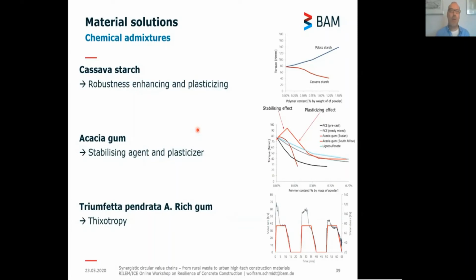And the other aspect that I was talking about were the chemical admixtures. All those agricultural wastes, before they can be converted into a reactive ash, often contain a lot of organic components, which can be converted into a chemical admixture. For example, we found out that cassava starch, other than potato starch, has a liquefying effect while it's still increasing the robustness. So here you can see the torque in a rheometer increasing with the dosage of potato starch, but you can see that the torque is decreasing with cassava starch. So the system is getting softer and better, and has a better workability. Also, acacia gum is very interesting.